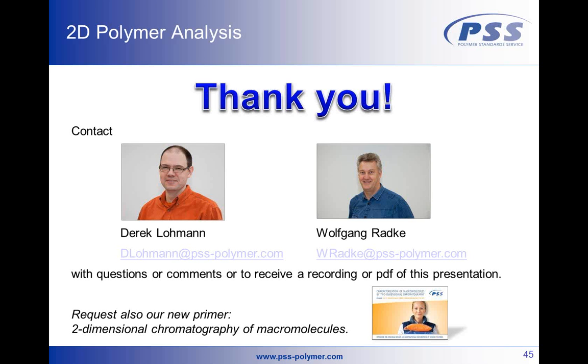If you use, for example, polystyrenes, and you adjust critical conditions for polystyrene, then it has been shown that the cyclic polystyrene elutes later under the critical conditions of the linear one. So probably the best method, if you have broadly distributed cycles with broadly distributed molar masses, would be to use critical conditions in the first and size exclusion chromatography in the second dimension.